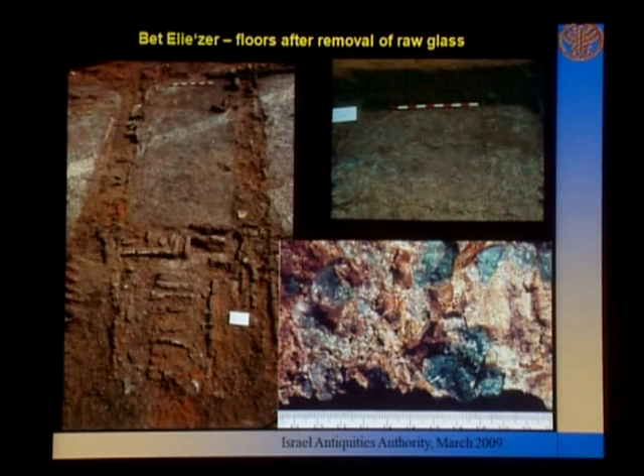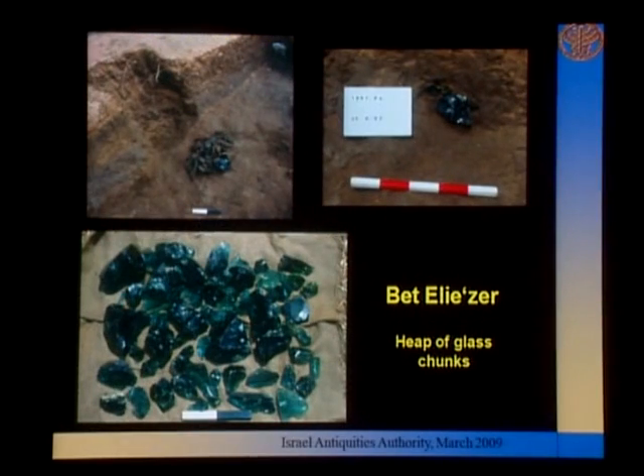Nearly all of the glass was removed, leaving only very few nuggets on the floors. This indicates that the production was successful and the glass was of high quality and suitable for remelting and vessel making. Only one concentration of glass chunks, totaling some 25 kilograms, was discovered. These were probably packed for sale and were left where we eventually found them.